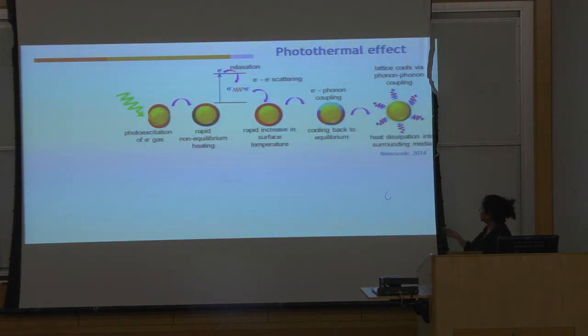What happens? Why does it break? As I said, it's the photothermal effect, a property of all metallic nanoparticles. When we shine light of the right color, where they absorb strongly, the strong absorption causes the electron gas to oscillate. The rapid heating here causes excitation, which the electrons then relax. And as they relax, the heat is going to go out to the lattice. There is nowhere else to go. And the nanoparticles don't have a lot of volume, so all the heat is dissipated in the surrounding medium. So it absorbs light, heats up, releases the heat to whatever is surrounding it.